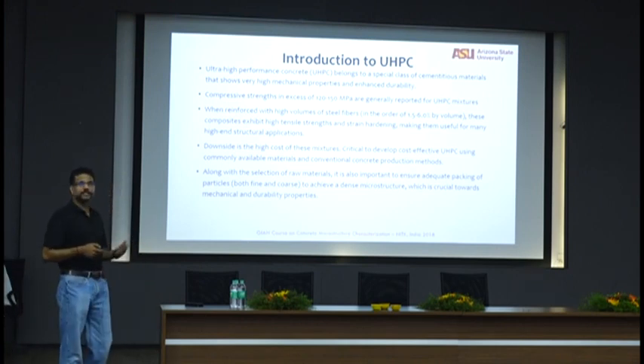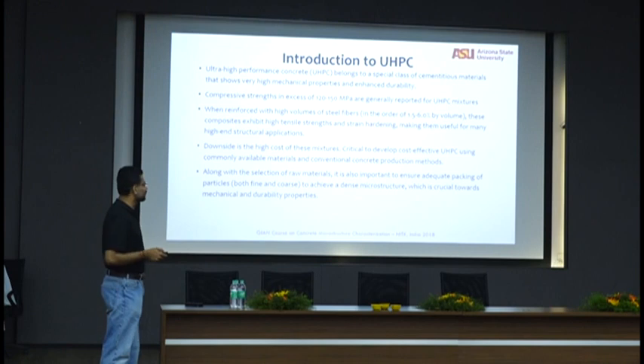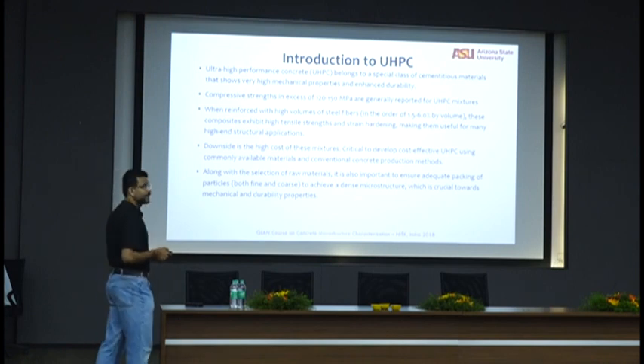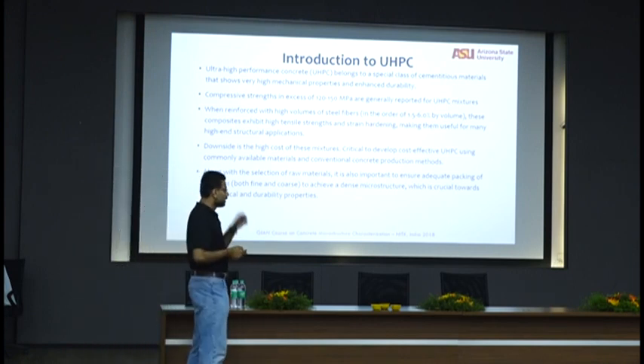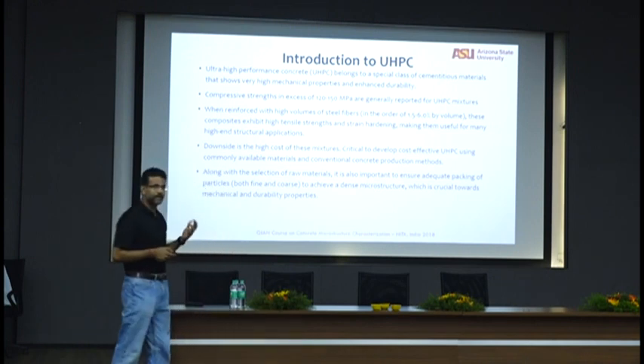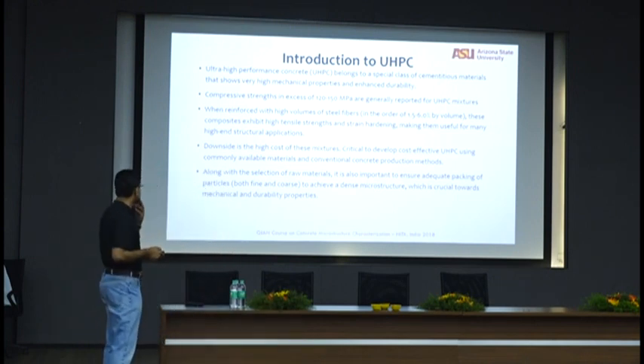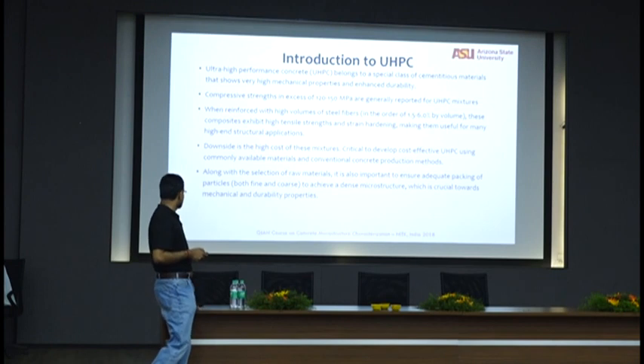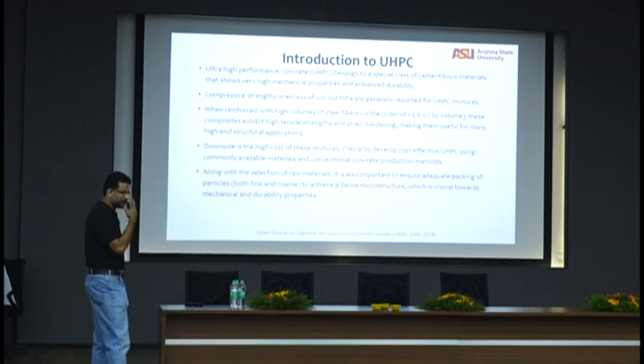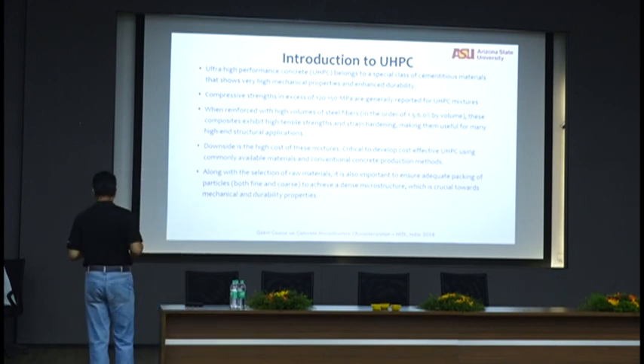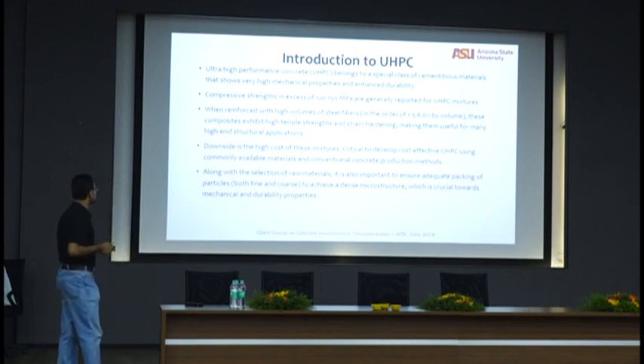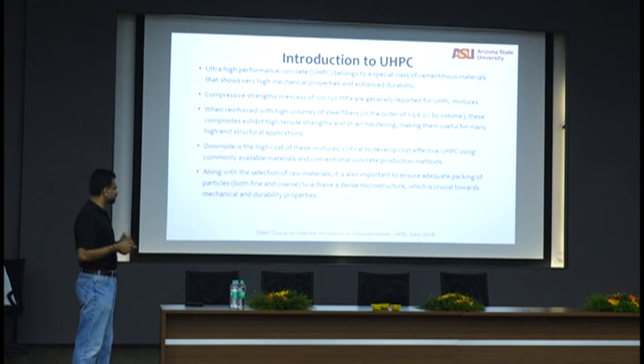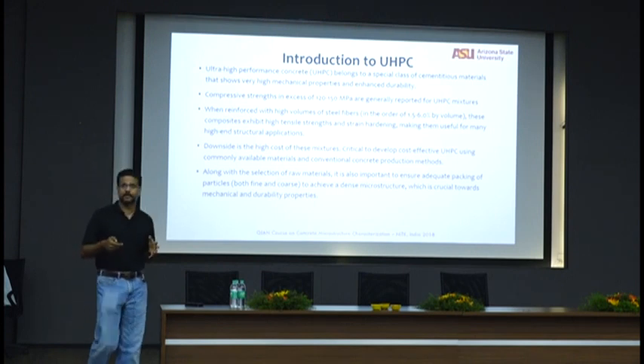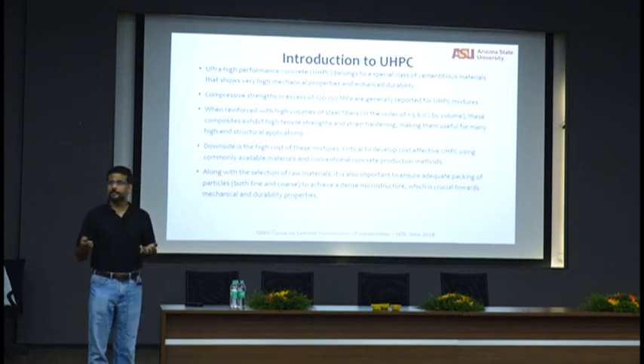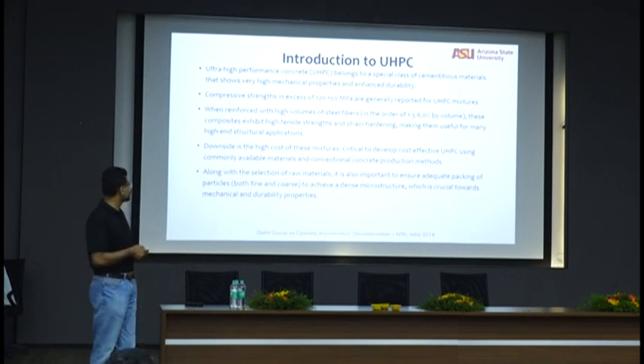When you reinforce it with steel fibers, 1.5 to 3%, they exhibit very high tensile strengths and very high flexural rigidities. They become strain hardening so that you can use it for high-end structural applications. Downside is the cost, as I said. So critical to developing cost-effective UHPC is really rational methods where you create a very dense microstructure. So basically what we have done is microstructural engineering to develop UHPC.